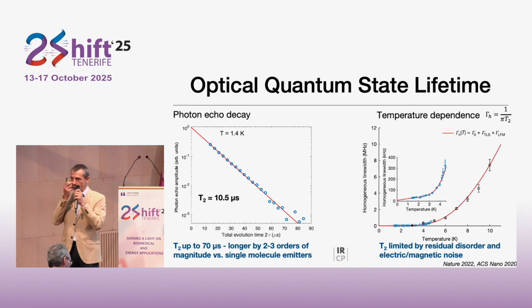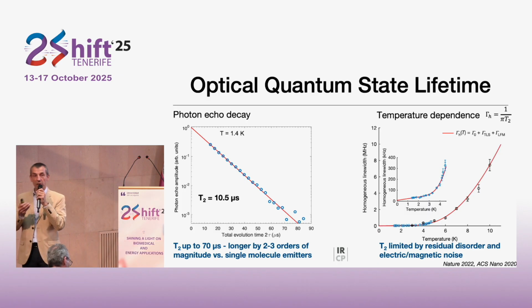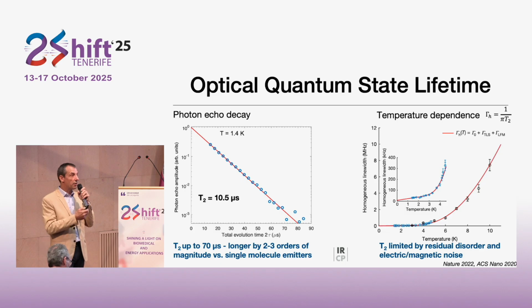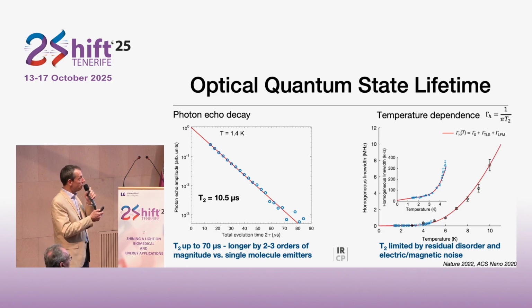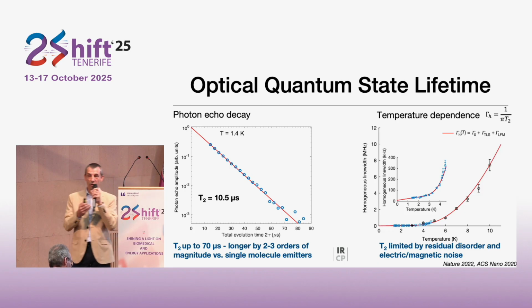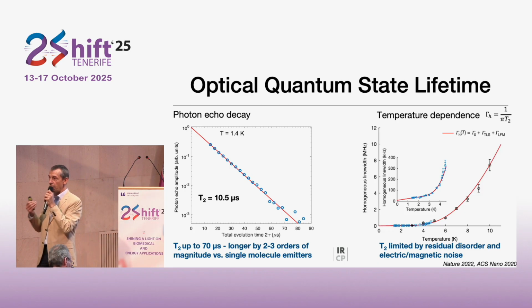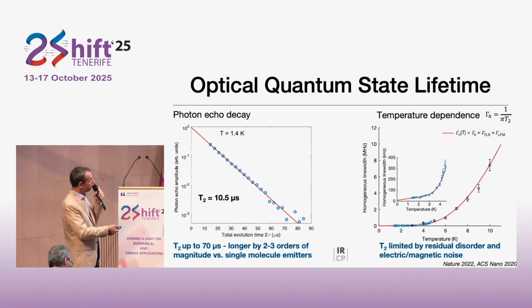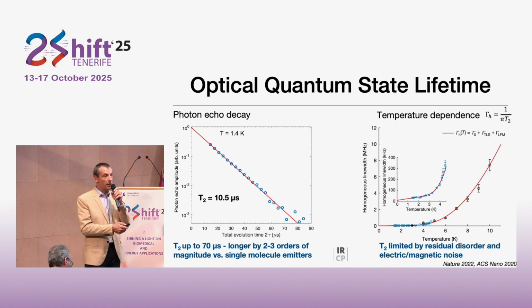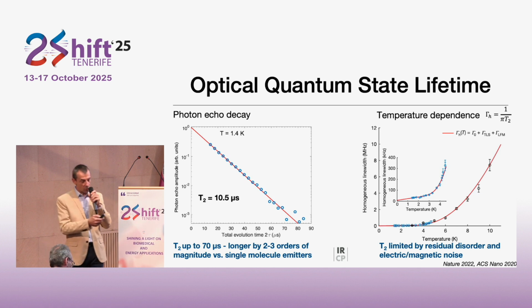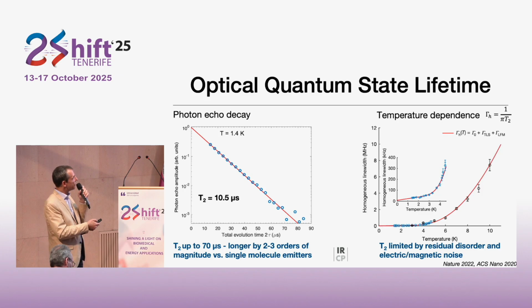Interestingly, these two contributions are very likely related to residual disorder in the crystals. So the first information we can get out of this dependence is that if we improve the way the crystals are made, the crystal quality of the materials, we may decrease these contributions. And indeed, we have a first indication that this is the case: with a better crystallization process, we can decrease this contribution related to disorder.